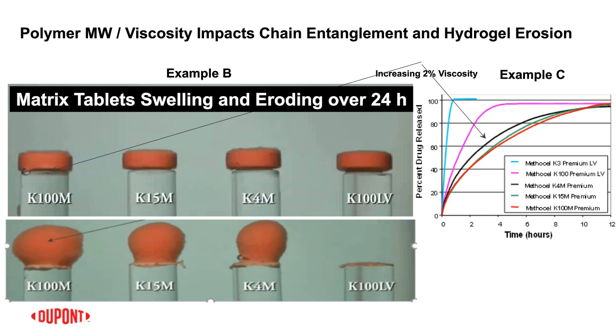You see that after 24 hours, there's obviously some of the matrix tablet remaining. There's more of the matrix tablet remaining with K15M in the formulation, and then finally, at least in this case, there's even more of the matrix tablet remaining after 24 hours when Methocel K100M is present in the formulation. And then, these are two different examples. Example B has a more poorly soluble type of API that's more dominated by erosion mechanisms of release. And then you see on the right-hand side example C, which is yet another type of API that's not quite as poorly soluble as that one in example B.